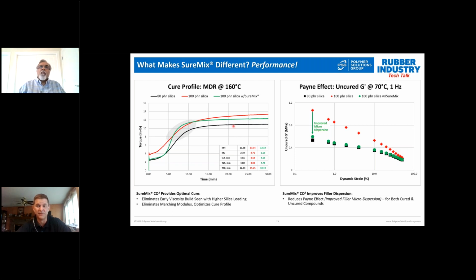If you look on the right-hand side, you see the Payne effect. So again, great use of RPA. We measure the uncured Payne effect. And you see here, if you're familiar with Payne effect, flatter curve is better, right? So if you see going from the black curve to the red curve, you see that the slope increases, right? So that means that you have poorer dispersion of the silica. So by putting in that extra 20 parts of silica, it becomes very difficult to get it dispersed, and you see that increase in the Payne effect. By using SureMix in this compound, we're able to decrease the Payne effect and flatten the curve. So you see the green curve is flattened close to the black curve, and that's with 20 additional parts of silica. So incredible improvement in silica dispersion using SureMix.